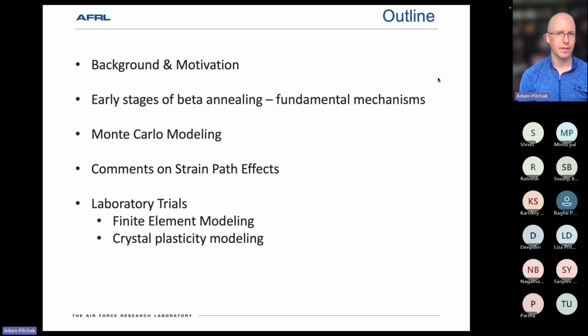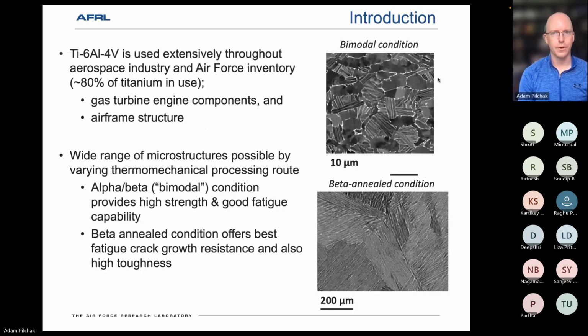Think a little bit about the effect of strain path on the formation of these abnormally large grains, and then talk a bit about some of the laboratory trials that we performed and used, both continuum FEM modeling as well as crystal plasticity modeling, to try to set some bounds and limits on some of the critical process parameters that are, again, driving this behavior. And then at the very end, I think I've got one or two slides maybe on the scale up effort.